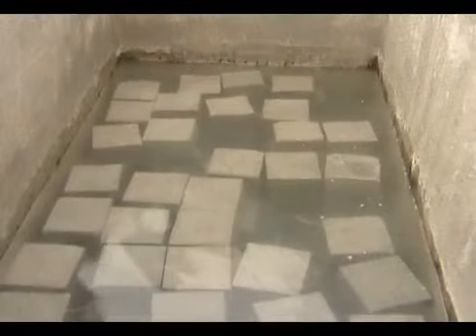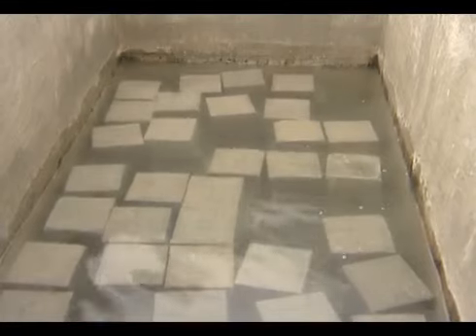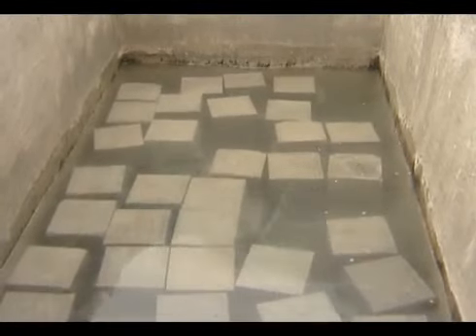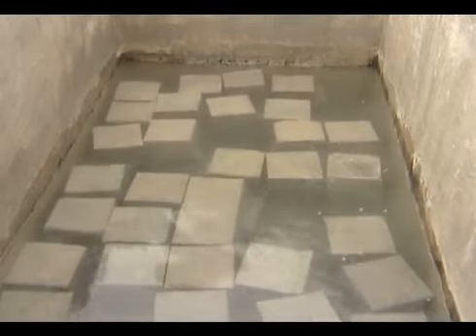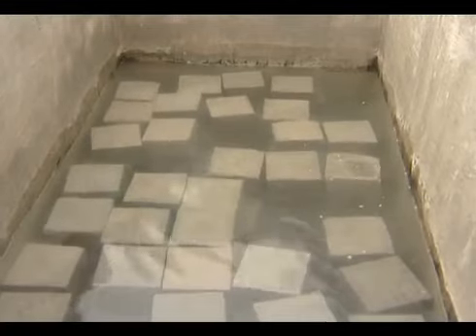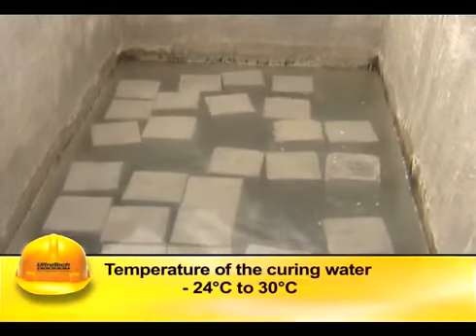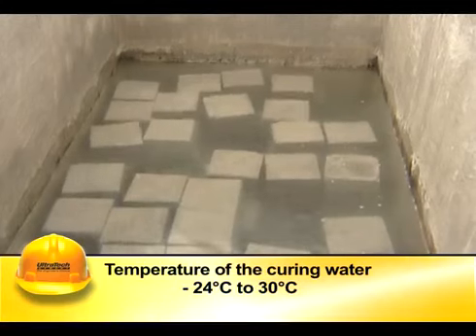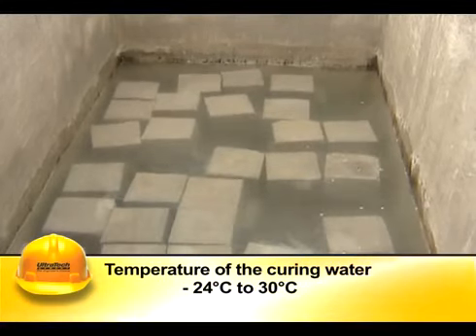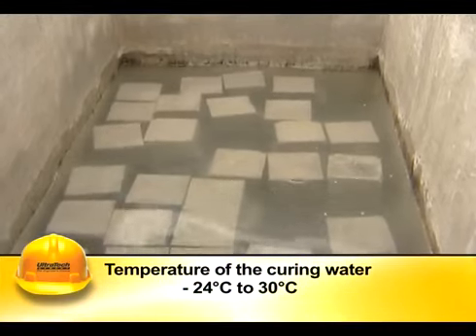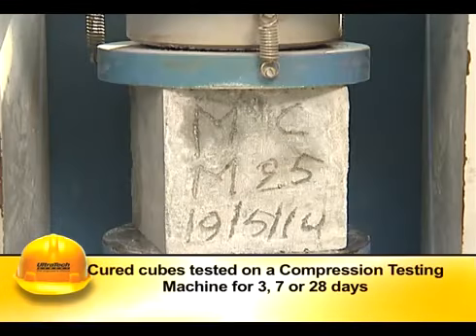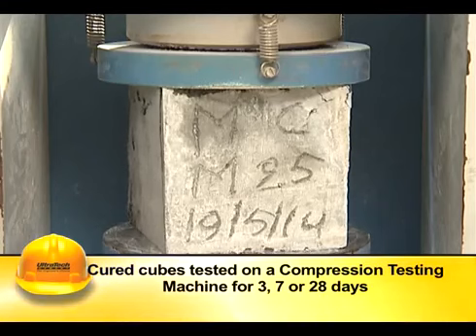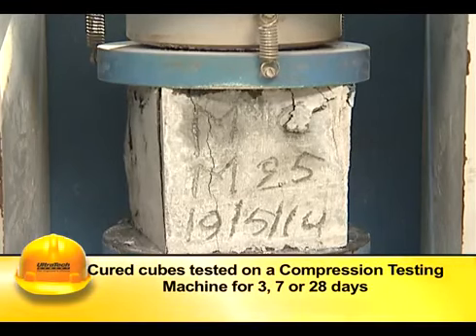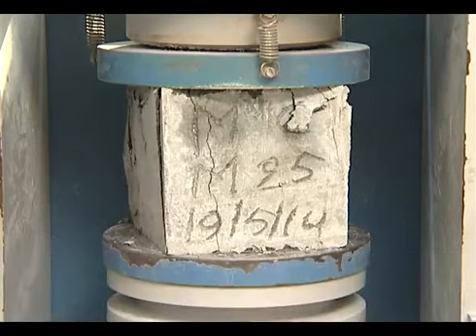After 24 hours, the mold is stripped off and the cubes are to be stored in water for further curing till it is taken out just prior to testing. Curing water temperature should be maintained at 24 degrees Celsius to 30 degrees Celsius. The cured cubes are then tested on a compression testing machine after 3, 7 or 28 days.